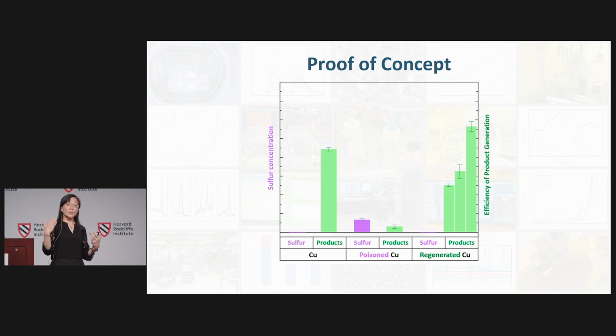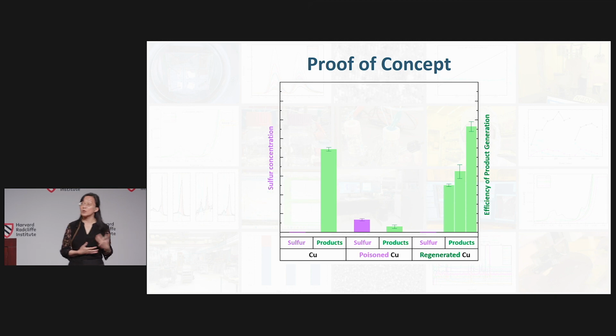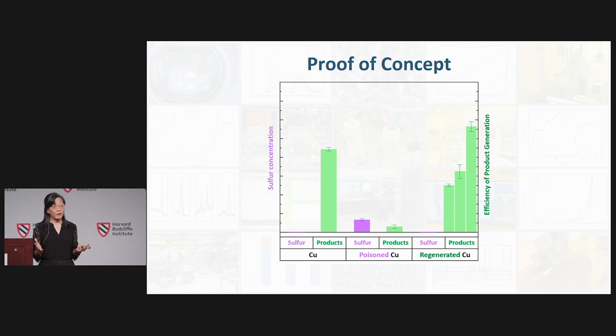2 of them appear to be not as good as the clean surface that we started with, and we ask ourselves why. So this is where that detection limit comes in. We remove the sulfur down to the detection limit, but we need a better, more sensitive technique to tell us if we truly remove all of the sulfur. We suspect there's still some sulfur there, probably on the order of a fraction of the monolayer, but we cannot detect it with our technique. But the effect was good.